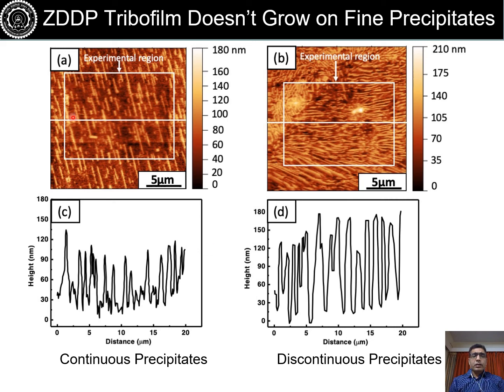Then we conducted an experiment on fine precipitate, which is the age-hardened alloy, and to our surprise, we could not see any film developed on this surface where the wear is also very small. So despite wear not happening to that extent, particularly precipitates do not wear easily in an AFM sliding experiment. Both type of fine precipitate did not show any tribofilm, and the reason we believe is because of the corrugation of the surface due to these precipitates. So if you see, the surface is highly corrugated, and that will result, if the probe is sliding over such sharp features, there will be large stress variation and also stress concentration.